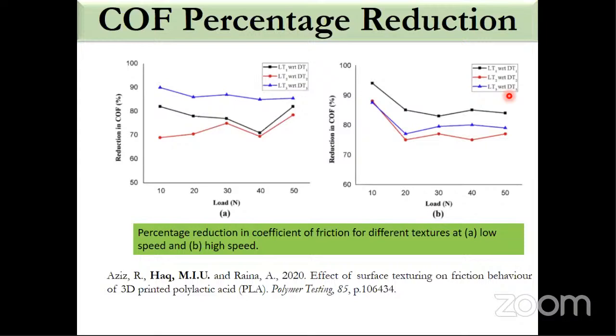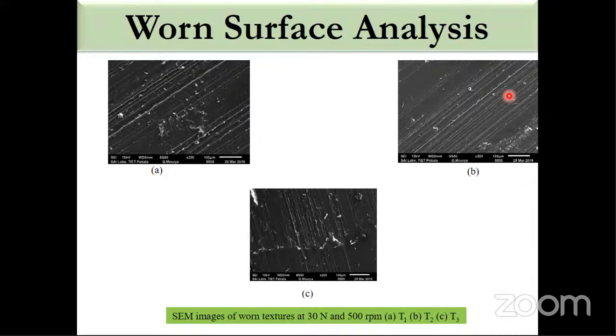So this work is already published. You can read it, and we did some SEM analysis of these worn textures at a particular load, and we could see very peculiar worn surface features, and smoother surfaces. In comparison to non-textured samples, we could actually improve the wear behavior, and very different and very peculiar worn surface features were observed because of the entrapment of the wear debris, and because of the storage of the lubricant in these small textured holes, or you can say these depressions.